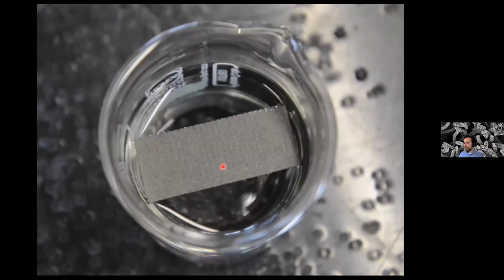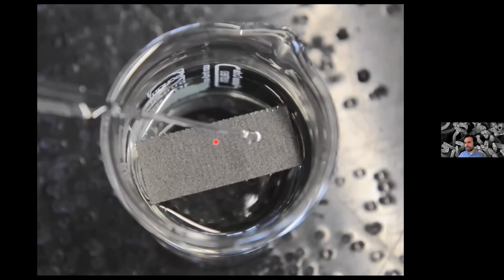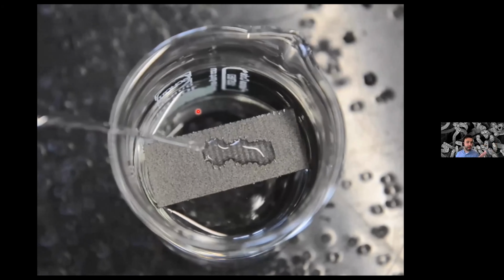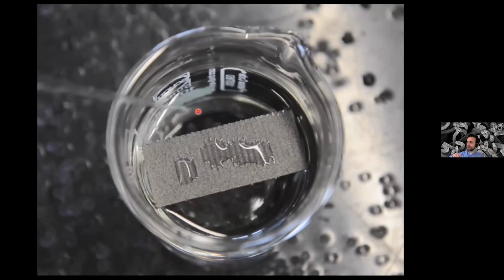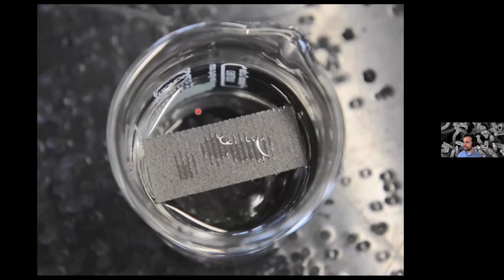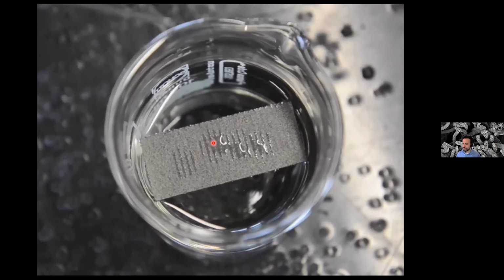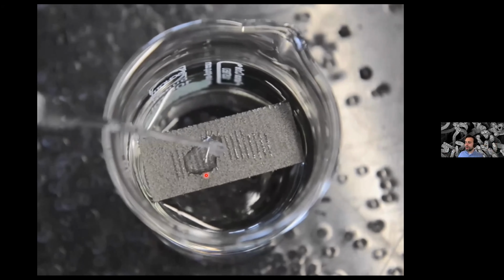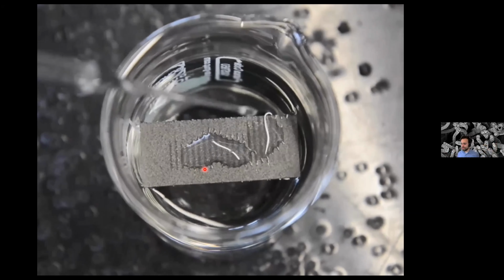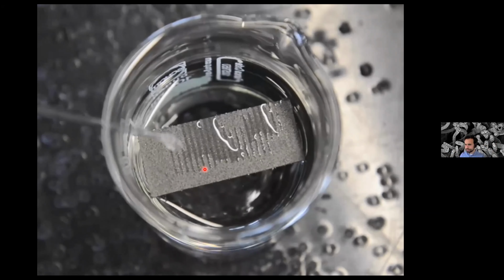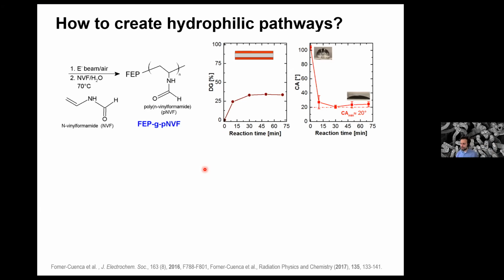Now, for those of you who have played with GDEs, you know that they are very hydrophobic. The water doesn't want to stay on the surface, it rolls off. And you can see how these materials look. You can essentially wick in the water through these patterns. All right, so very briefly about the chemistry, we used N-vinyl formamide, which is a monomer that polymerizes after electron radiation. This happens at low temperature, 70 degrees.